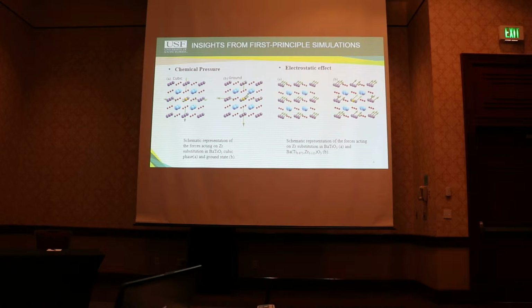Here we have the two main insights that we gain from our 0 Kelvin simulations. The first is the chemical pressure that's induced. Here we have both the cubic and ground state after we've already done a substitution of titanium for zirconium. It's important to show both because this chemical pressure will happen regardless of the phase or the temperature. The chemical pressure is shown with the green arrows pointing outward, as the substitution for zirconium induces a negative chemical pressure due to the larger atomic size of zirconium.